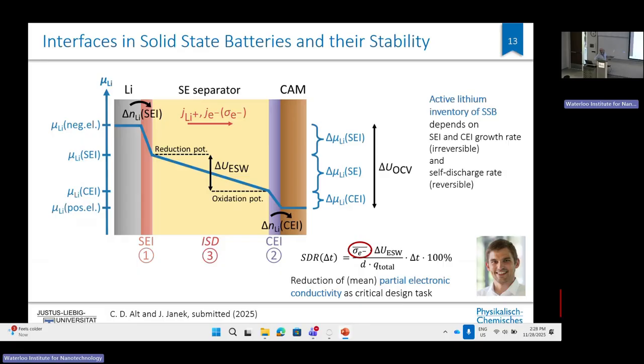The anode has a very high chemical potential, and the high chemical potential here can reduce your solid electrolyte. If it reduces the solid electrolyte, because the reduction potential of the solid electrolyte is not high enough, then you will get an SEI. You will get a layer of degraded electrolyte.